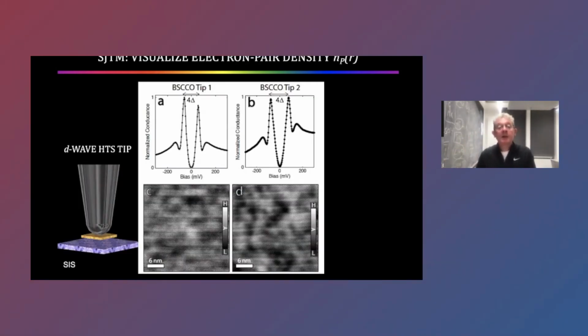Okay, so to do that for BSCCO, we had to make a high Tc tip, which we did by exfoliating a little piece of BSCCO onto the tungsten tip. After that process, we can tell that the tip is superconducting because the energy gap is 4 delta, not 2 delta, in the single particle spectrum. And we can tell directly by visualizing that we still have atomic resolution. These are two completely different tips. And this technique has been repeated in other labs as well. So it's known to work.